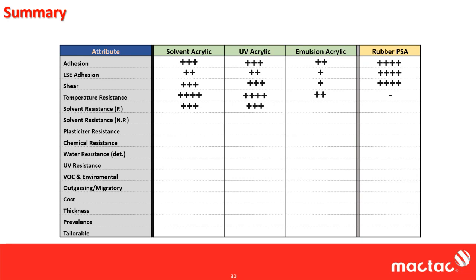Depending on the amount of crosslink, it determines how much they swell, how much they don't, as well as some monomer selection. But emulsion acrylics, they'll do okay, but they will solvate. Rubbers actually do very good in terms of polar solvents. You can pour alcohol on a rubber, and because of the difference in polarity, it's not going to touch it.